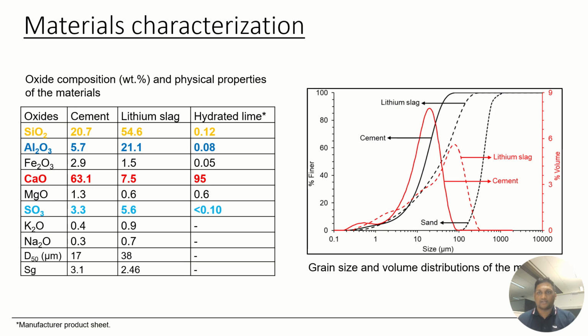The material characterization of lithium slag will provide vital understanding for the experimental design, reaction kinetics, and hydration product formation. Here we can see the silica, alumina and sulfate concentrations of lithium slag are higher compared to cement. On the other hand, calcium, magnesium, and iron are lower in lithium slag. The median particle size of lithium slag is 38 micrometers, 2 times that of the cement, and the specific gravity is 2.46. The grain size and volume distribution curve show that roughly 5.8% of the total volume is occupied by 100 micrometer lithium slag particles.